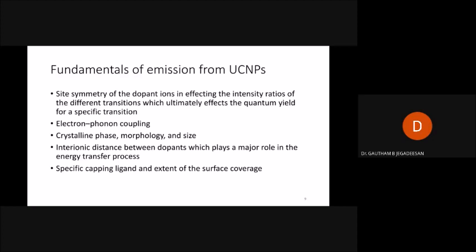Now, when you increase the dopant concentration, the distance will decrease, so concentration quenching will happen. So it is very, very important to maintain the interionic distance in a host to get perfect upconversion. The last one is a specific capping ligand and extent of the surface coverage.